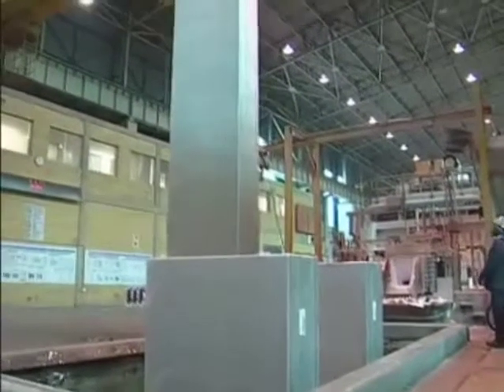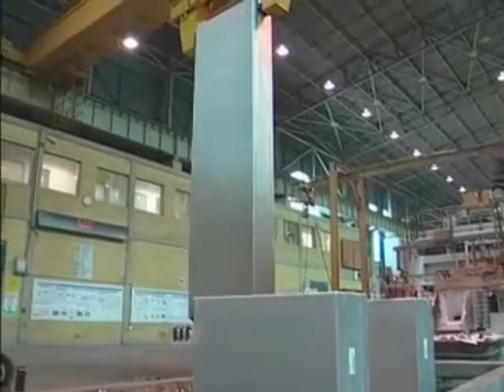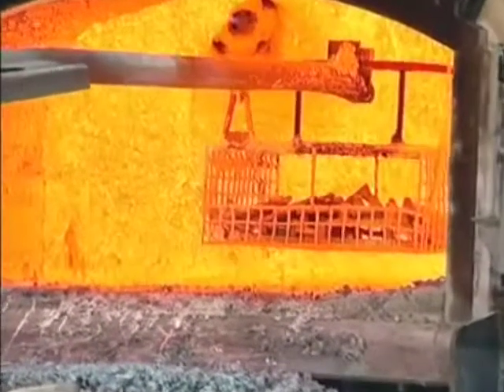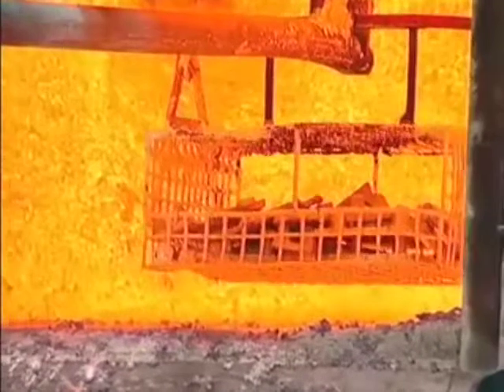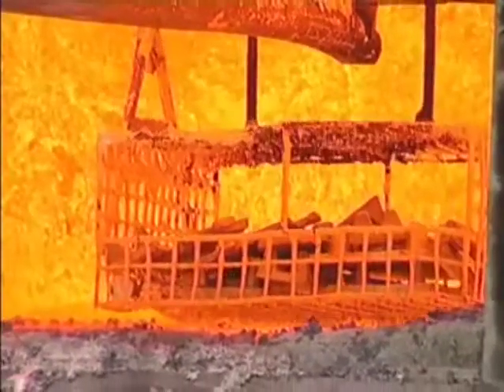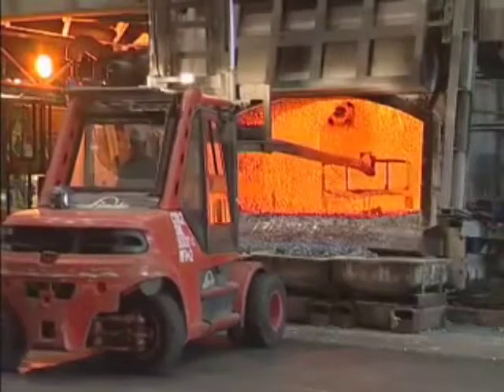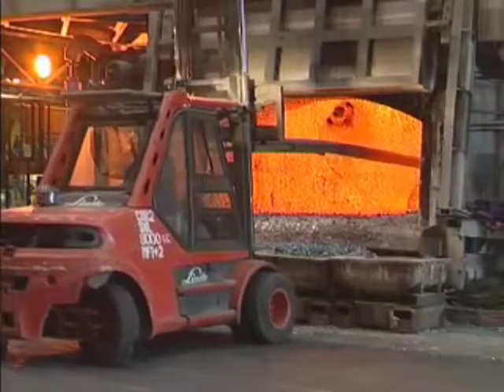One of the major products that we produce here is can end, which is 5182 aluminium, which contains up to 5% magnesium. We were having difficulties with extended periods of melting and adding the magnesium. Adding up to 5% magnesium in a 65-ton furnace takes quite some time, and we were losing time and weren't able to supply enough of the 5182 through to our rolling plant.